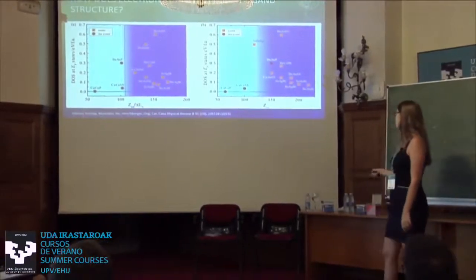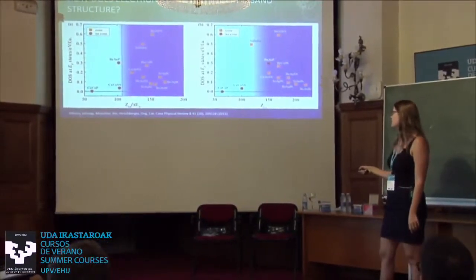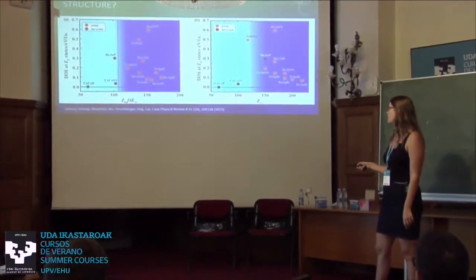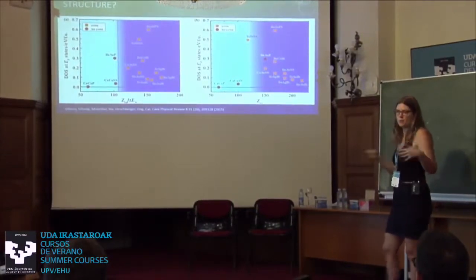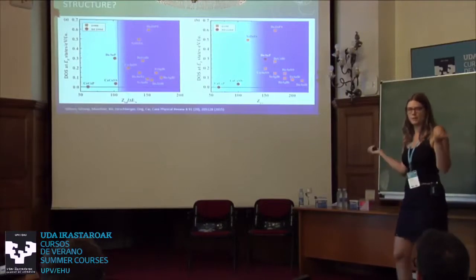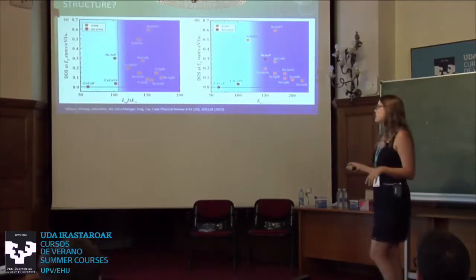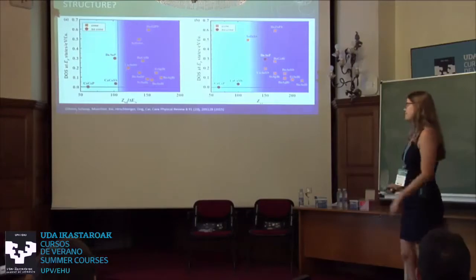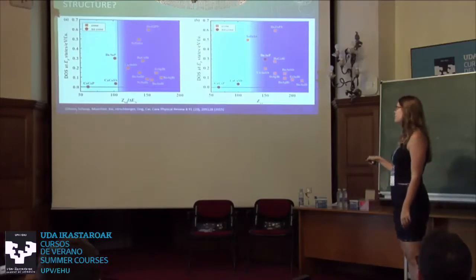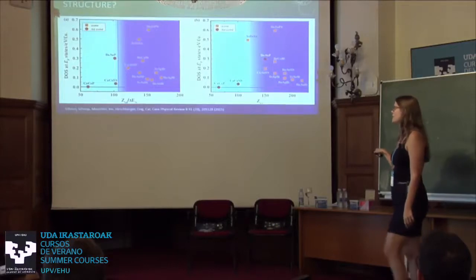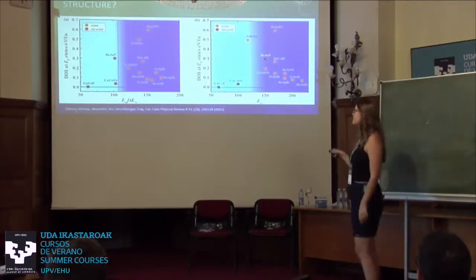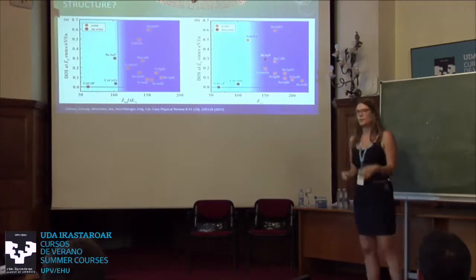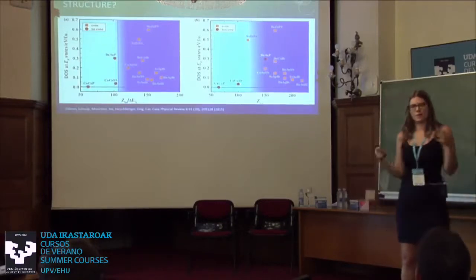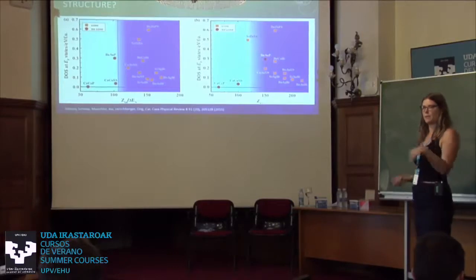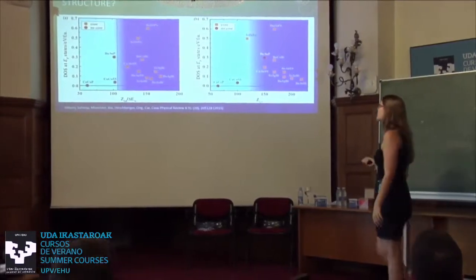And then we made two different plots versus the x-axis. On one plot here, we plot the total nuclear charge, which is somehow a measure for the amount of spin-orbit coupling because it increases with Z, divided by the electronegativity difference of the elements. And then in this plot you see that the red points don't even have a direct crossing, and for the orange points, the direct crossing is there. And so there's a clear phase transition basically of when you can have that and when you don't have a 3D Dirac semimetal. So is there a band inversion or not, based on spin-orbit coupling and electronegativity difference.